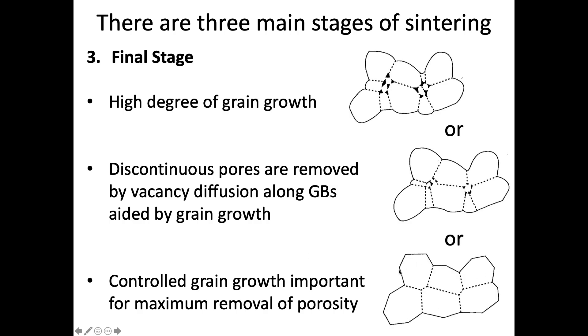But the important part here is that controlled grain growth is important when we're talking about porosity. And so this is kind of the ideal case where throughout this process, through grain growth and these various mass transport mechanisms, we're able to eliminate that empty space. But again, key is on controlled grain growth. That's what we saw in the last lecture with the addition of MgO to Al2O3 to control grain growth.